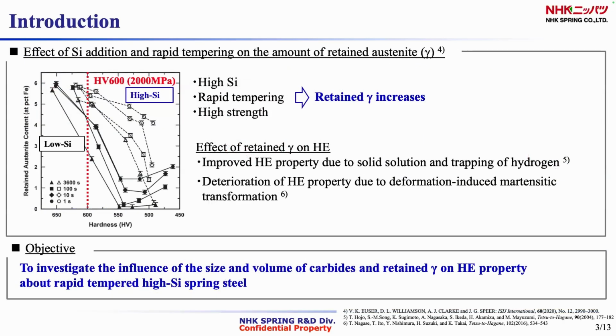On the other hand, it has also been reported that the amount of retained austenite increases when silicon is added and rapid tempering is performed. The effect of retained austenite on hydrogen embrittlement includes improvement in its property due to solution trapping of hydrogen, or deterioration due to deformation-induced martensitic transformation. Therefore, the objective of this study is to investigate the influence of the size and volume of carbides and retained austenite on hydrogen embrittlement property of the rapid tempered high silicon spring steel.